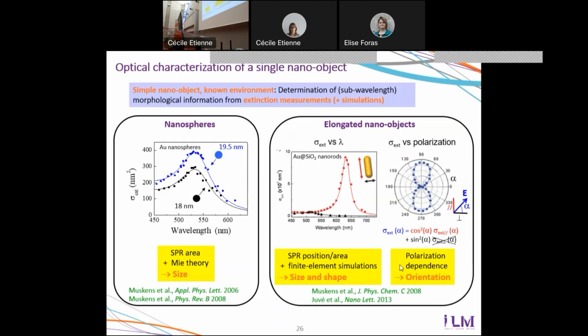So here you have a few examples for simple objects. On the left, nanospheres. A nanosphere will produce more absorption and scattering if it is bigger. Remember, in the formula I showed, the response was proportional to the volume of the object. It means that from the quantitative measurement of the amplitude of this spectra, we can deduce what is the size of the particles that we investigate by comparison with models. We can also do the same for more complex objects, for instance, elongated nano-objects such as gold nanorods. So from the polarization-dependent response, by comparison with simulations, we can extract the size of the object, the shapes, that is both the diameter and the length of these objects, and also, as I just described, their orientation, how oriented they are on the surface.